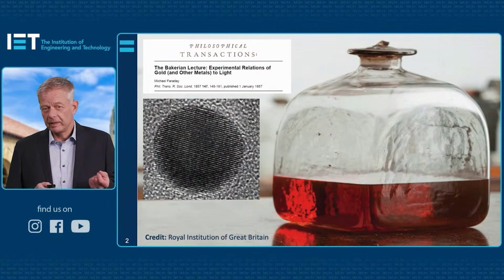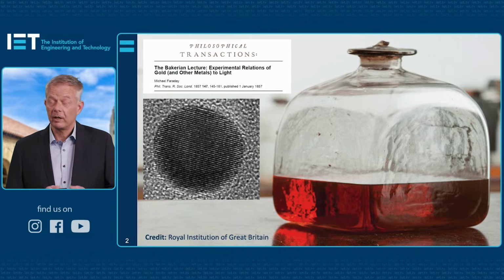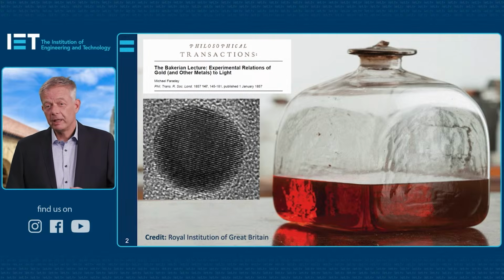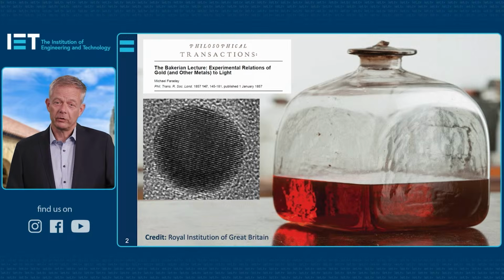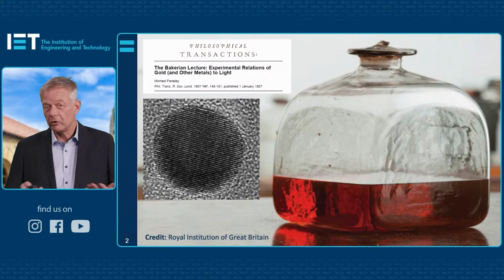He noted that tiny little metallic particles of gold and silver show very strong colors, such as the vial here with colloidal nanoparticles. Gives this beautiful red ruby color, which later on was shown, as shown in the electron microscopy image on the left, to be due to gold nanocrystals inside this colloidal suspension, typically on the size scales of several tens of a nanometer.